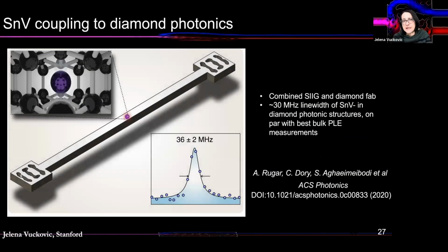Very recently, we've also been able to incorporate tin vacancies in fabricated devices, and we've shown that there is no degradation in their properties, even in optical devices and relatively close proximity to surfaces. We see line widths of 36 megahertz, which is comparable to the best measurements in bulk diamond.